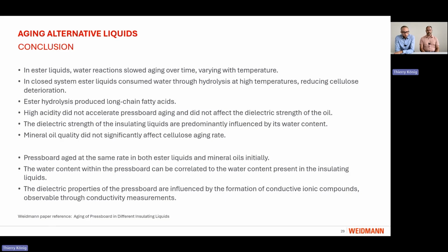The water content in the pressboard can be well correlated to the water content in the insulation liquids, and the dielectric properties of the pressboard are also mainly influenced by the water content, and that could be observed by the conductivity measurements of the pressboard. This experiment is also published in a paper from our side named Aging of Pressboard in Different Insulation Liquids.